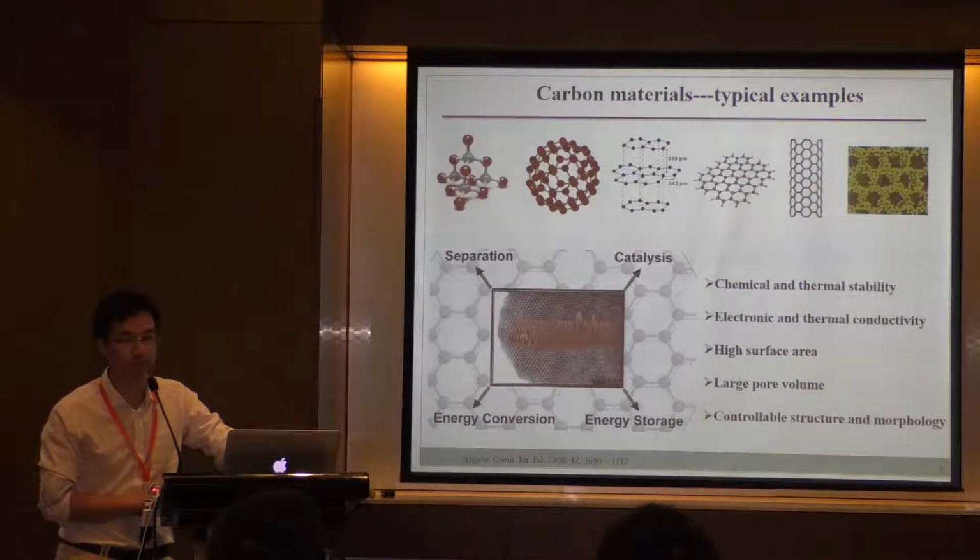One reason is that it is very difficult to get monolayer carbon, and in reality the layers may aggregate or be stuck together, and we may get several hundred square meters per gram. And also in such a planar structure, if we load nanoparticles on this kind of support, the nanoparticles may easily or rapidly detach from the support.